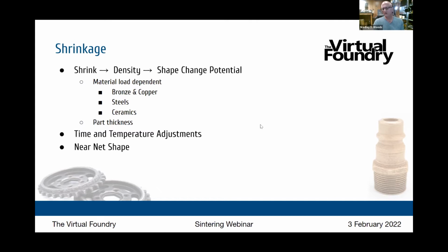So here's where you put it in the kiln, and you'll run it up to about 90% of the melting point. You never get to the melting point, that would obviously destroy it. So a good sintering temperature is between 80 and 90% of the melting point. And what happens is the particles, first they become kind of sticky and they contact each other. And then through a process called atomic diffusion, which is essentially just surface tension. It's the same thing as when you see two water droplets connect to each other. The same thing is happening but with metal. And the parts connect. And at that point, you still have porosity. You have gaps between the particles where it's not connected. At this point, the part has shrunk about 7.5%.